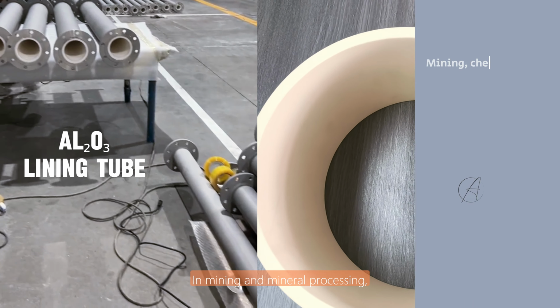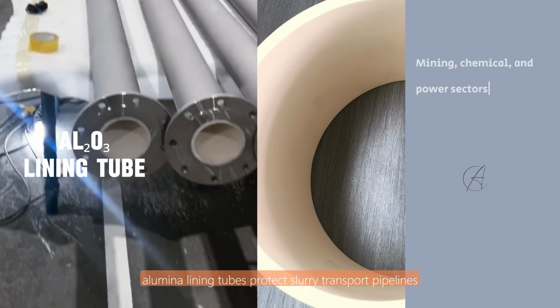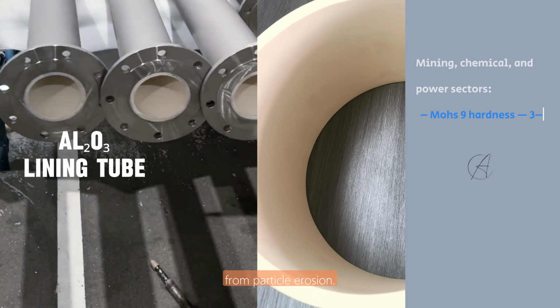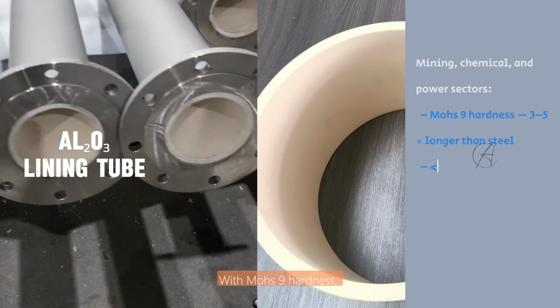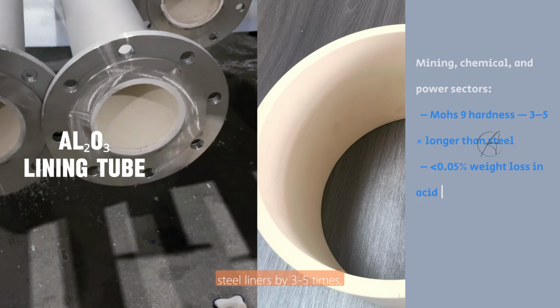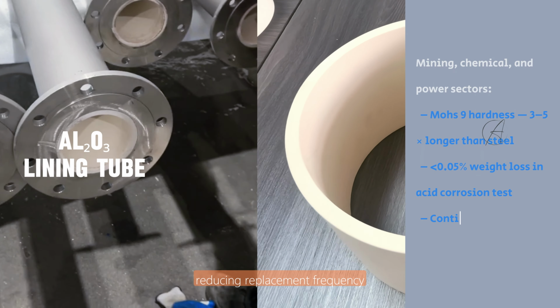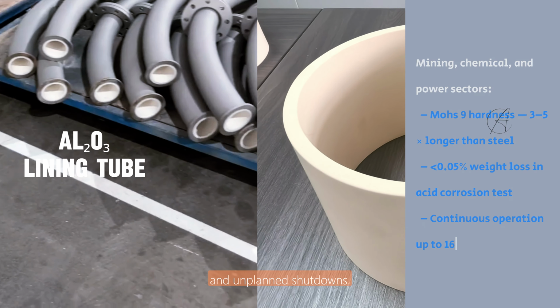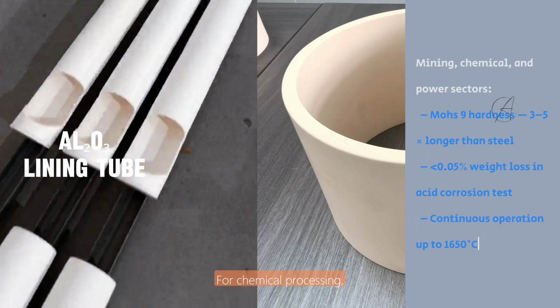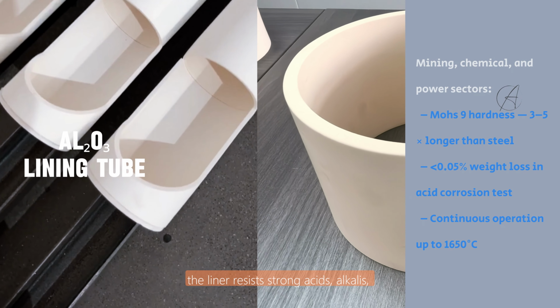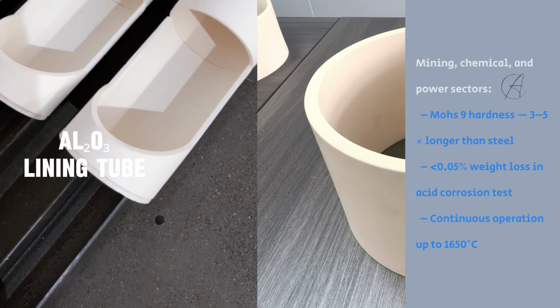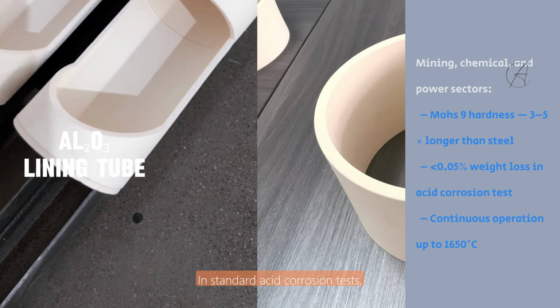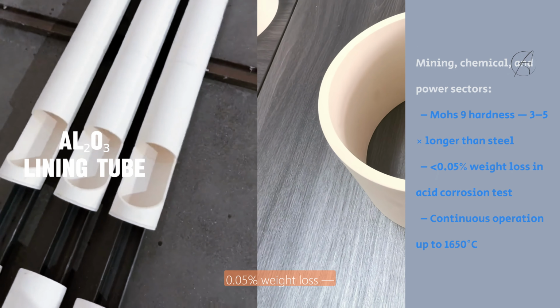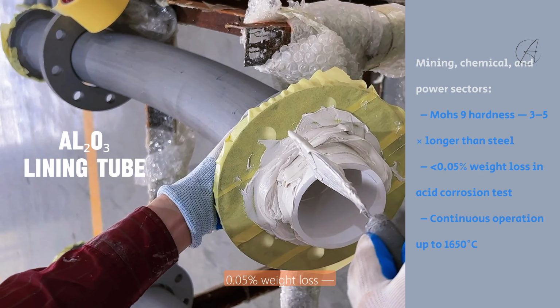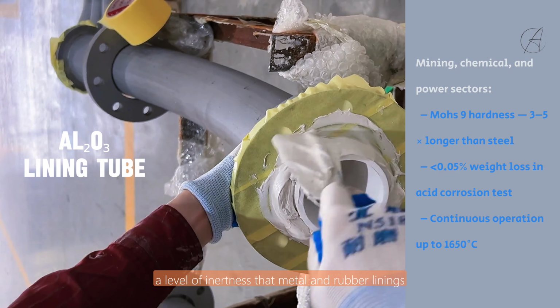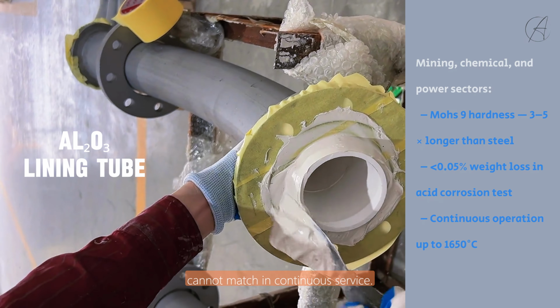In mining and mineral processing, alumina lining tubes protect slurry transport pipelines from particle erosion. With Mohs 9 hardness, the ceramic surface outlasts steel liners by 3 to 5 times, reducing replacement frequency and unplanned shutdowns. For chemical processing, the liner resists strong acids, alkalis, and chloride solutions. In standard acid corrosion tests, high-purity alumina shows less than 0.05% weight loss, a level of inertness that metal and rubber linings cannot match in continuous service.